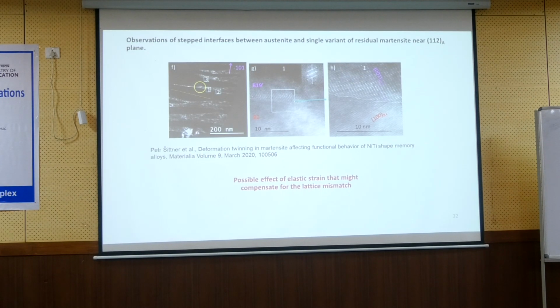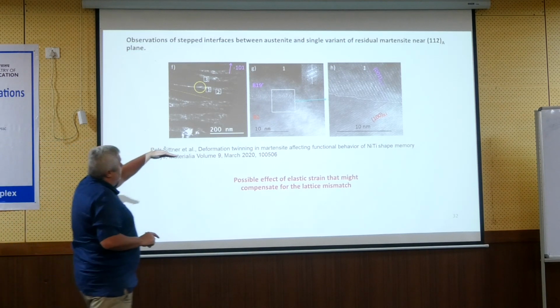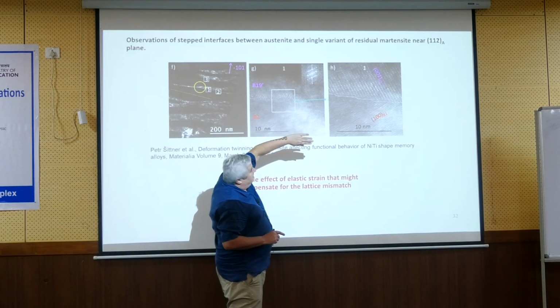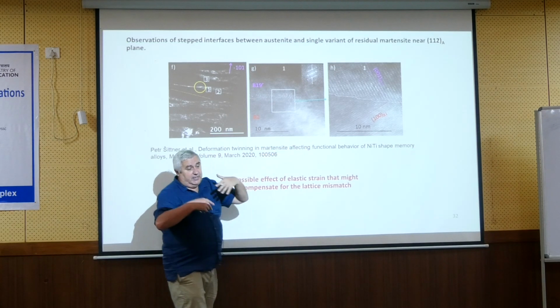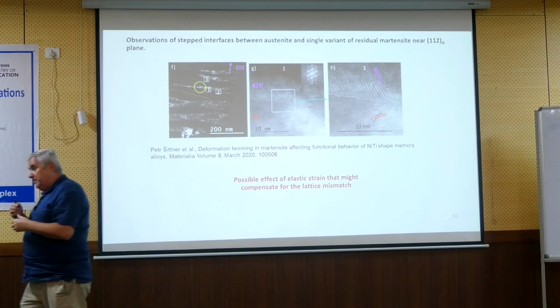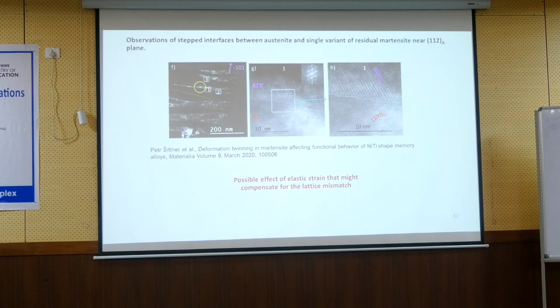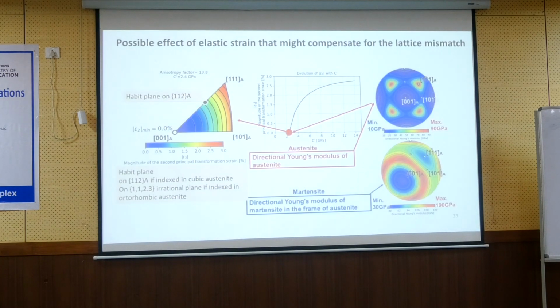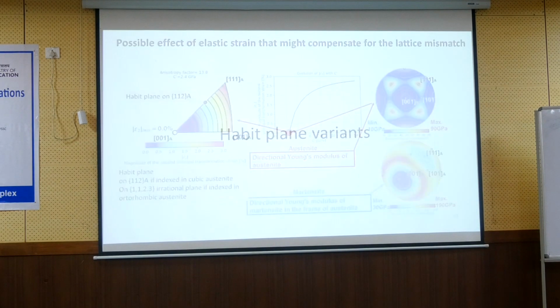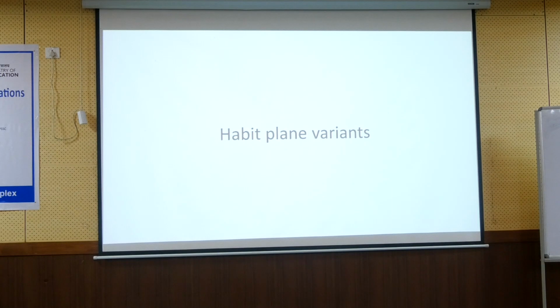And the other possibility is to rotate the habit plane, because now this lattice could be any kind of lattice. So we did the analysis, we rotated the habit plane, and simply found that around the 112 plane you will get a minimum where the lattices are compatible. So I will go very quickly to finish this lecture.